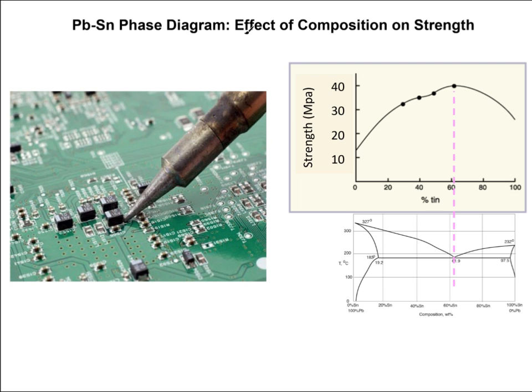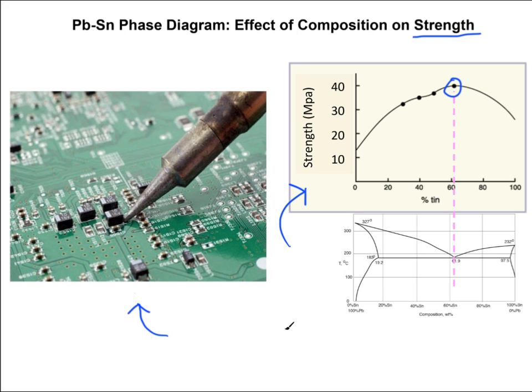Why do we care about microstructures? Microstructures vary with the composition, and they have a direct effect on strength. Looking at this diagram, we can see that the highest strength occurs at the eutectic composition. It also happens to be the composition that produces the lowest melting point. A common application is soldering — the solder most commonly used for microchips has the eutectic composition because it has the lowest melting point and highest strength. By the end of this video, you should understand why.